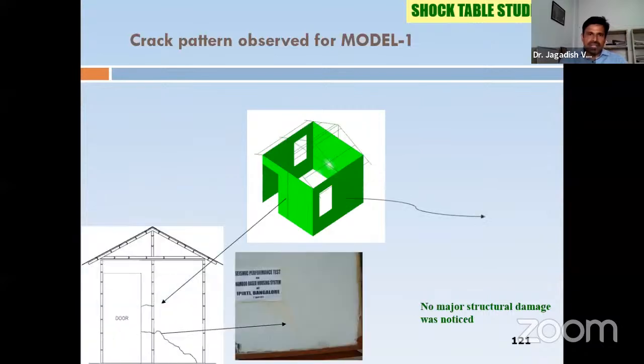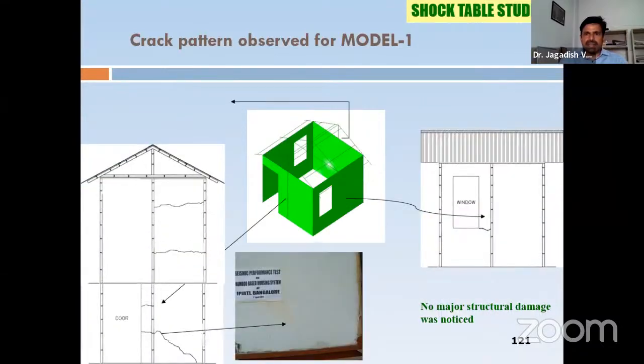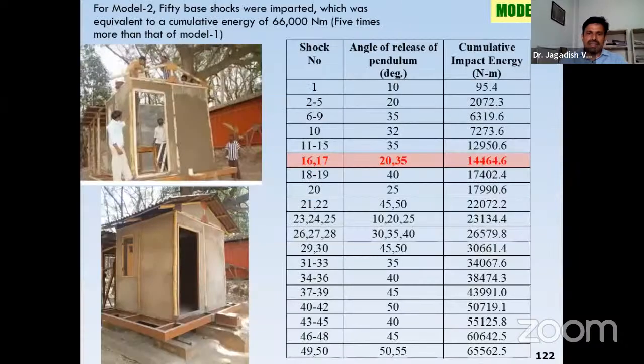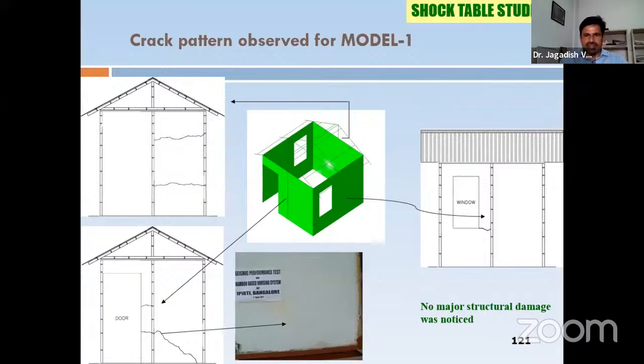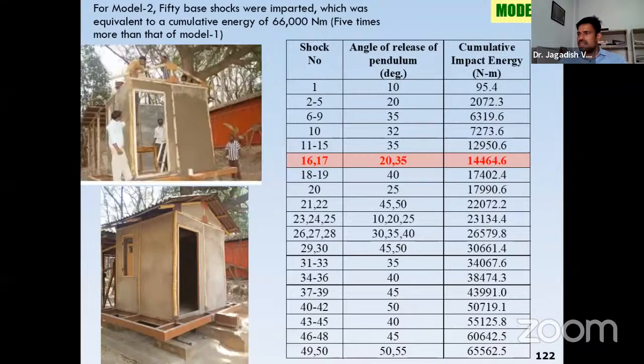After giving 15 shocks, you can observe minute hairline cracks in the first model, but there was no major structural damage. Then we built the second model and gave almost 50 shocks, almost 5 times more than the first model. You can see the cumulative impact. In the first case, we gave only 14,000 newton meter of impact, and this is almost 5 times more impact on this particular building.